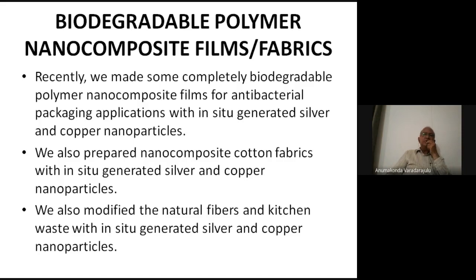But then we thought, why don't we make some nano composite films, biodegradable nano composite films, especially for antibacterial applications in the medical field. But there are two methods of making these nano composites. First thing is you make the filler separately, nano filler separately, and then take a polymer matrix and disperse it in it. This is the dispersion method. But unfortunately, this dispersion method is a two-process method. Not only that, the dispersion is not uniform. At many places, you will be getting agglomeration so that the composite will not be uniform.